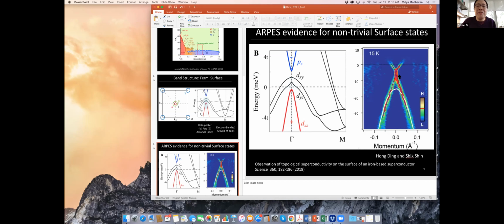No, just 50-50. And if I may comment, this was just done. I posted the link to the archive paper. So there is an appearance of the topological surface state as a function of tellurium concentration and disappearance of superconductivity. No, but I'm asking about a bulk, not a surface state. Yeah, there is appearance of a surface state which is indicative of a band inversion in the bulk. And that's as a function of tellurium. It actually happens not at 50%, but around 55. Yeah.